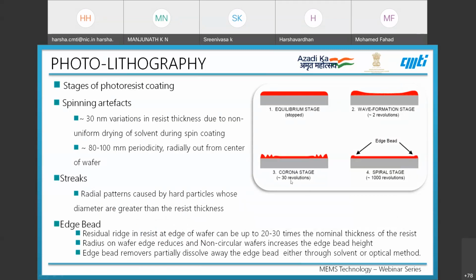Then there is approximately around 30 revolutions, at which the photoresist will look like this. And at the end, say about 1000 revolutions for a cycle, we will end at the spiral stage with edge bead at the corner or circumference of the wafer.